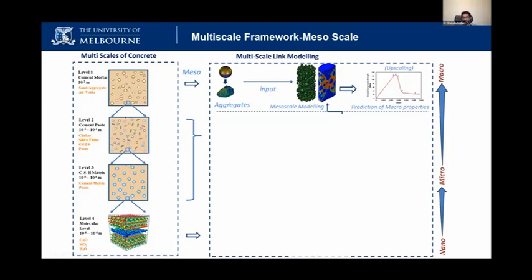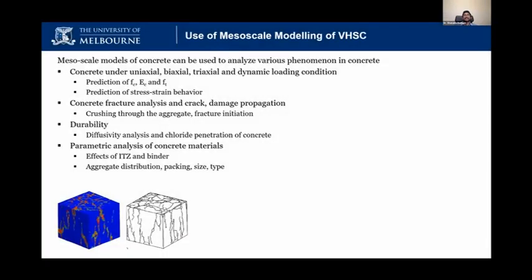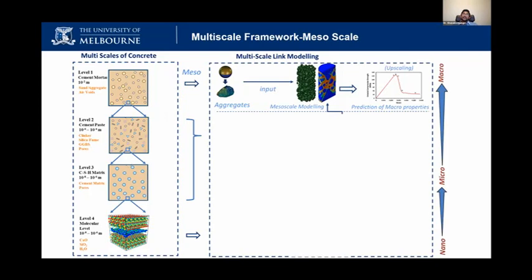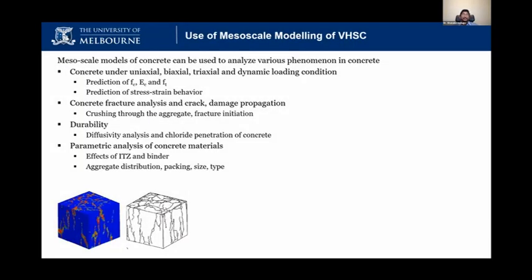So in the mesoscale, we basically generate the aggregates, then we model them with the binder, and we simulate in computers, with advanced computer models and software, and we can predict the result. This is the stress strain graph. From that we can get the elastic modulus and the strength, and what constituent fails, whether the problem is in the aggregate, in the ITZ, the interface between the aggregate and the binder, or the mortar. Depending on that, we can improve. We can even select the best aggregate to blend with the mortar properties. We can do that kind of simulation using mesoscale modeling. This work, Sadiq's PhD, he worked a lot on mesoscale modeling, and he did a lot of new things I will explain.